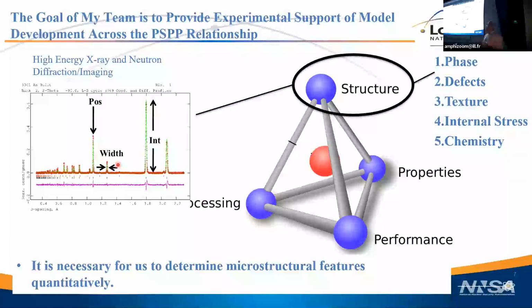And that's perfectly valid. The reason she did that is because she's trying to go really fast. She wants to get data as fast as possible. But that's not helpful at Los Alamos. At Los Alamos, I need to know this is what the phase fraction is doing, right? This is the value of the residual stress, not, oh, look, there is a residual stress. So in the measurements I'm going to show you, we make sacrifices in terms of speed so that we can get quantitative microstructural information, and you'll see that.